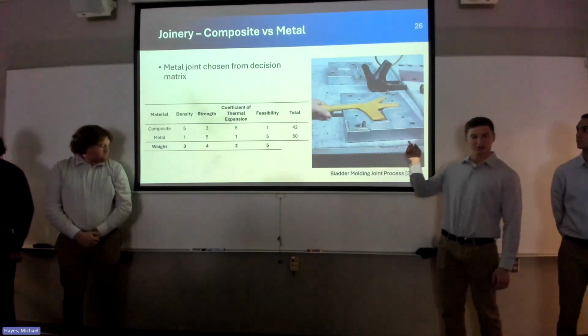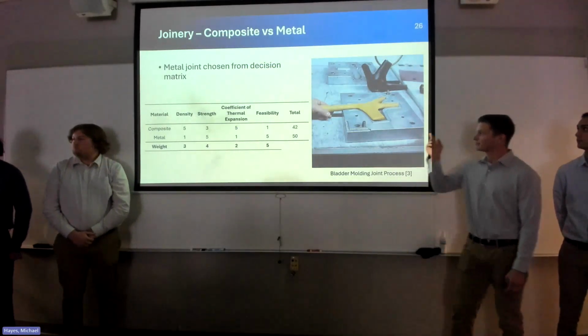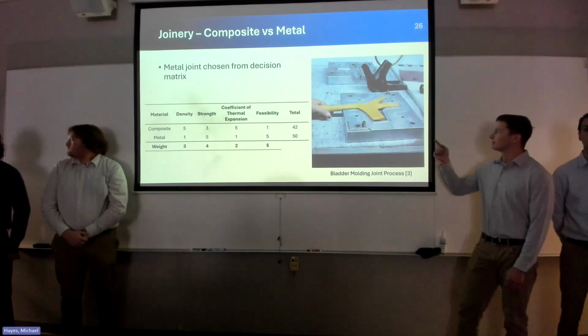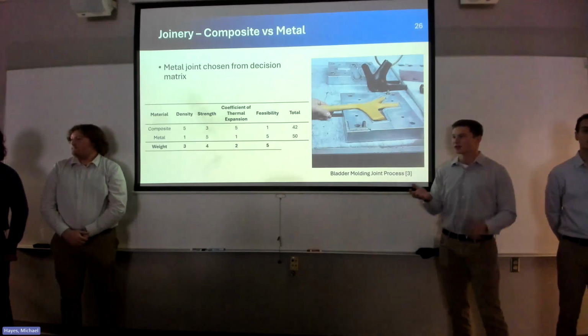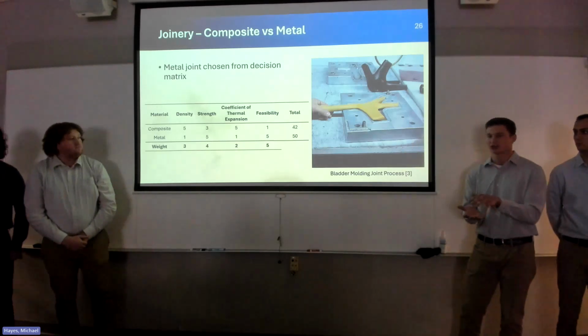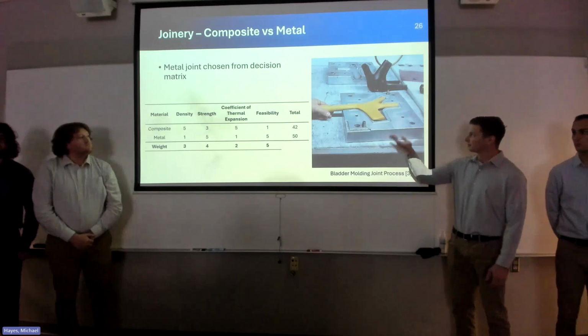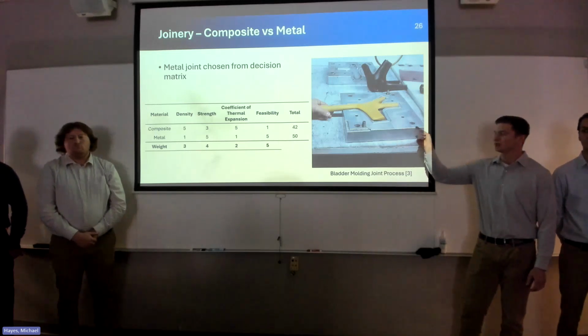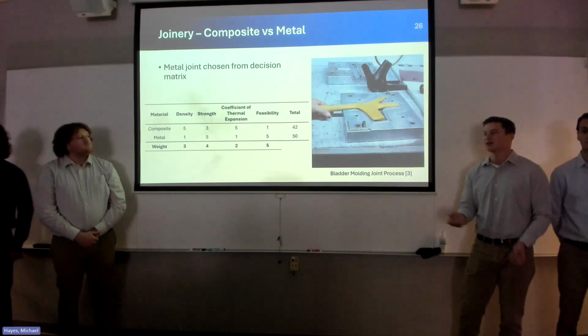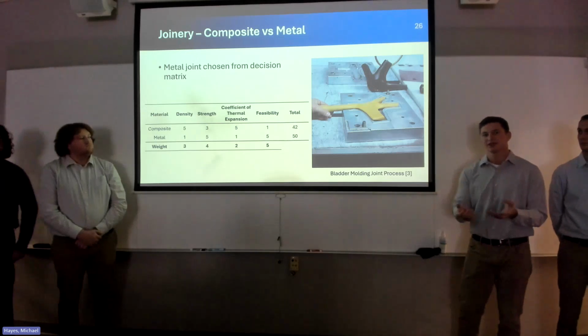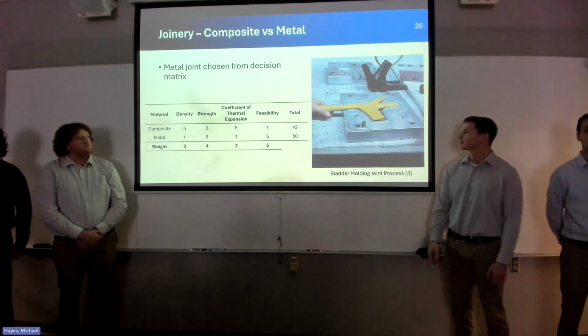Looking at a sample composite joint here, you would have a bladder molded process. This is a die, as you can see here. So this would kind of form your outer shape or geometry of the joint. Then you would lay in your fabric of the composite. You would lay in a bladder, or basically a balloon. And then once this die is closed, you would inflate that, which forms the inner geometry of your part.